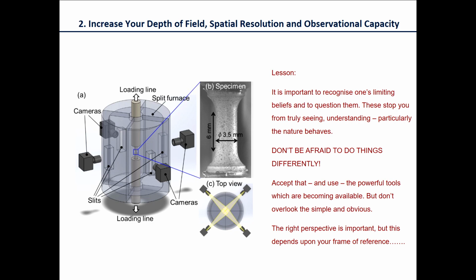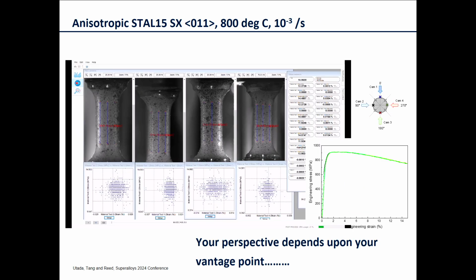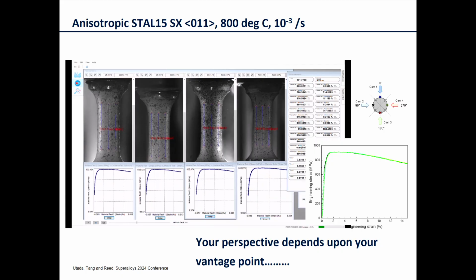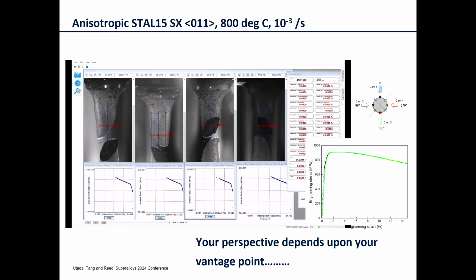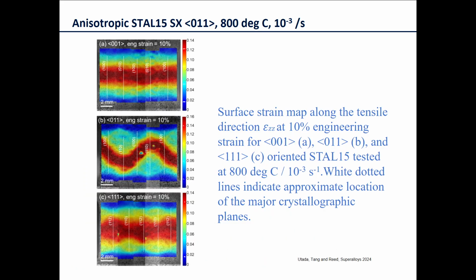Here, the perspective ended up being very, very important. And you can see here that when we test the material from 4 different angles, or we measure the deformation, the perspective that we have here is very different depending on which camera we use, even though it's exactly the same test. So what this teaches me anyway is that the perspective depends very much upon your vantage point. And you can see from these sorts of measurements that we were able to map the surface strains as a function of the circumference of the material for different orientations of this particular material.